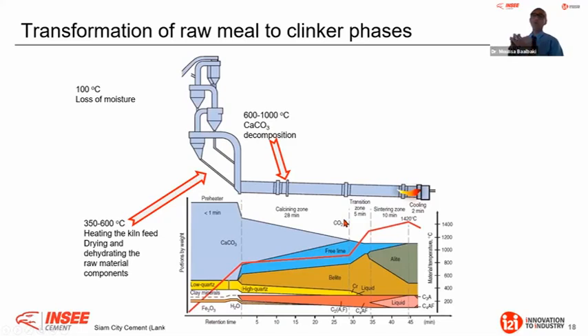And this is where, when we say production of clinker, it has a very high CO2 footprint, because for every ton of clinker, we all know now that we are producing, depending on the process we use, approximately 0.8 to 1 ton of CO2. We can say equivalent to 1 ton. For every ton of clinker is the same ton of CO2. Therefore, if I go to OPC, for example, for every kilogram of cement is the same kilogram of CO2.